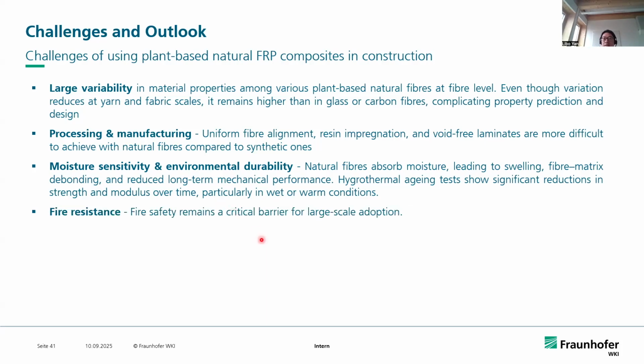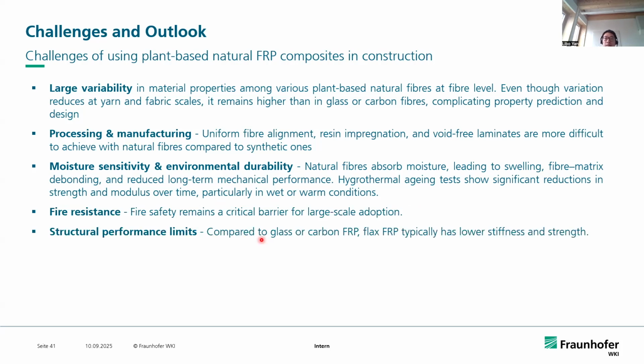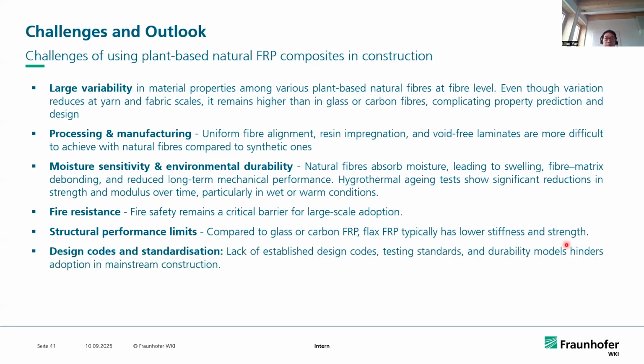And fire safety is a critical issue for all kinds of nature-based material, like flax, like wood. And compared with glass or carbon FRP, the flax FRP typically has a lower stiffness, which is about 10 gigapascal. The strength is about 250 megapascal, so much smaller compared with glass or carbon FRP.